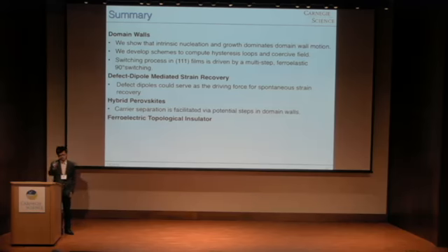You're saying when the thickness of the film is even smaller than the size of the critical nucleus, then probably homogeneous switching becomes the dominant mechanism. And in that case, the depth of the double well potential, even though it gives a pretty large coercive field, starts to make sense. But my comment is that in this work we are of course interested in bulk response, but for a thin film, when it's too thin, is that really a bulk property? So I think the idea of homogeneous switching is definitely very interesting, and it's also part of future research.